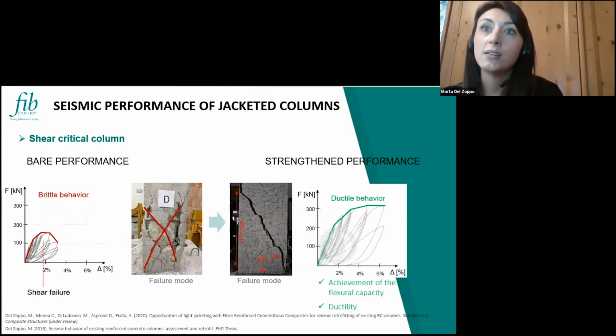So if you look more in detail about the failure mode and the shear crack, we can see how the fibers that are crossing the crack are trying to bridge the two edges of the crack until we have the complete debonding of the fibers. Of course, we are working with short fibers, less than 20 millimeters length. So when we have the complete debonding of the fibers, we have the complete opening of the jacket.